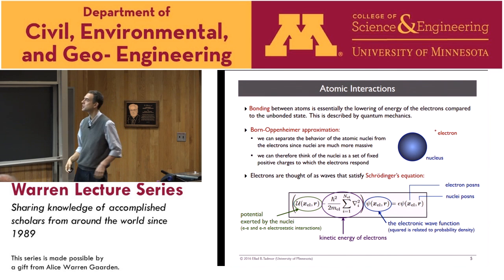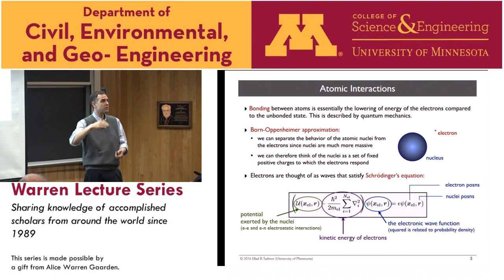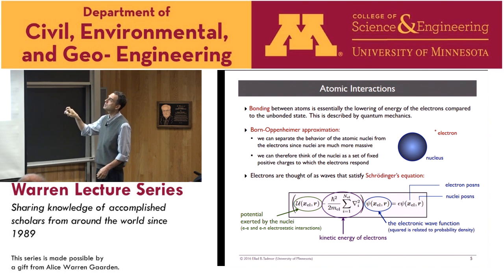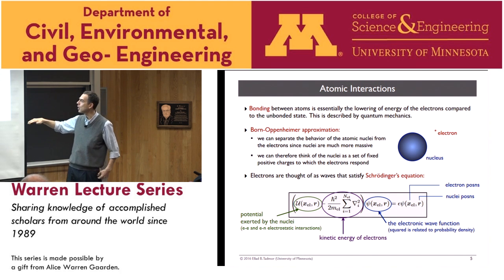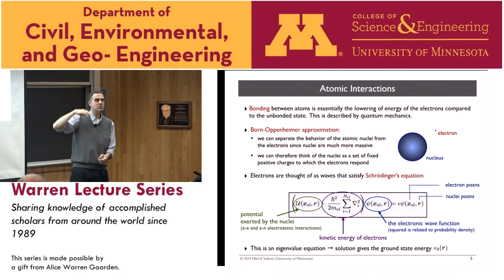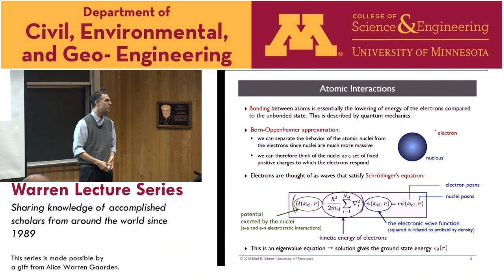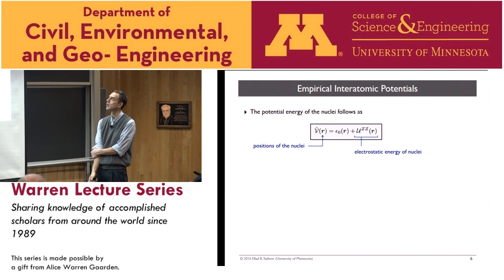And if you look at this, you see that this is an eigenequation, right? You've got something times psi equals epsilon times psi. And so you can solve for the states, and that's really the quantized states that we're all familiar with. But subject to the Born-Oppenheimer approximation, if the nuclei are really moving very slow, then what you're always interested in is the ground state of the electrons. So not the excited levels, but for a snapshot of the nuclei, the electrons always have time to find their ground state. That's the Born-Oppenheimer approximation. It's not always correct. There are many processes where this is not correct, but for typical things that we are interested in for solids, it tends to work well.